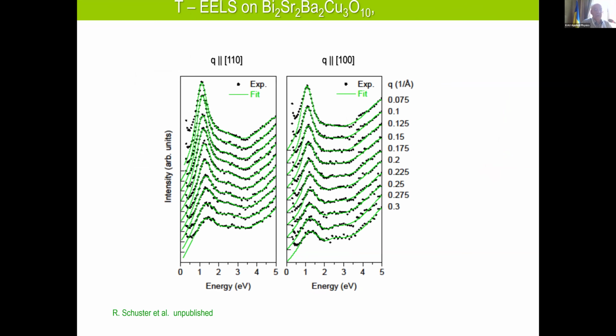Now, these are recent data on a tri-layer system, and again we see well-pronounced plasmons, but we also see some discontinuity at a momentum which is below this Lindhard critical wave vector. And also in the width, in the right panel, we see some discontinuity. And at present, we don't know exactly what it's coming from.